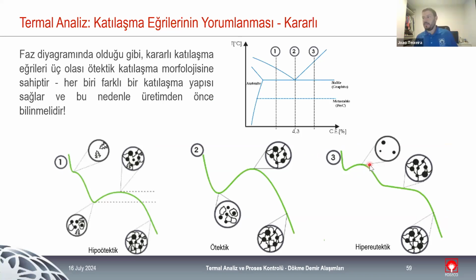When we are dealing with the stable solidification, we have the 3 types of solidification that we already discussed: hypoeutectic, eutectic, and hypereutectic, and each one with the differences between the phases being formed first. Hypoeutectic with austenite being formed first, and the graphite being formed at the eutectic. The eutectic point, where the graphite and austenite form at the same time, so the inflection that we have at the eutectic is bigger because we have both phases being formed at the same time.